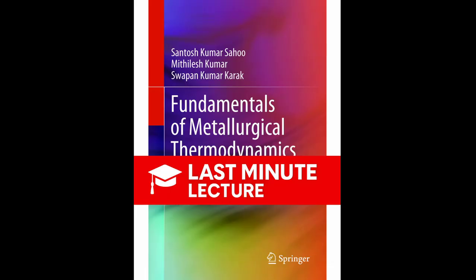Case IV. Delta H is negative, meaning it's exothermic, it releases heat, and delta S is positive, meaning randomness is increasing. So if we plug this into delta G equals delta H minus T delta S, the delta H term is negative, and the minus T delta S term is also negative because T is positive and delta S is positive. So you're adding 2 negative numbers. The sum of 2 negative numbers has to be negative. This reaction is always spontaneous at any temperature.